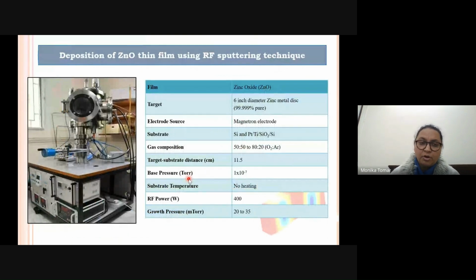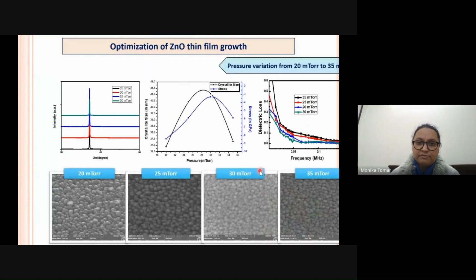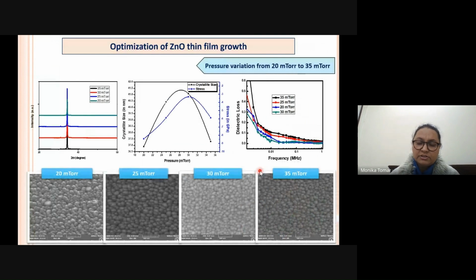The most important component is the zinc oxide thin film deposition, which we have deposited using the RF sputtering technique, which is available in our lab. And these are the typical deposition parameters which are used for the growth of the zinc oxide thin film. Now we have optimized the zinc oxide thin film so that the SAW device could be fabricated on that, and the losses are as low as possible so that the acoustic losses reduce.